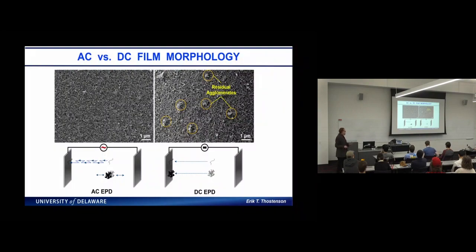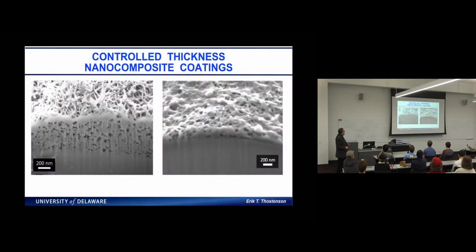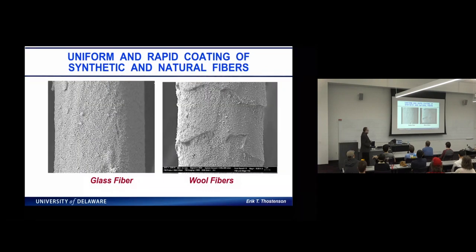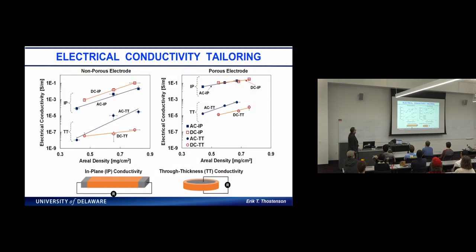And then this is just an example, as I mentioned, for the AC and DC, that for the AC, that nonlinear mobility gives us a net deposition. And we can control the thickness of that coating, and it's like this sponge-like coating. You see here it's maybe a couple hundred nanometers thick. Here, this is less than 200 nanometers. So again, it's really a fiber level coating, and we can coat not just high performance fibers, but now we can coat things like cotton or wool or polyester. And you see the wool fiber has this kind of cuticle structure, and we have this uniform coating still on that as well. And we can also have a lot of control over tailoring the electrical conductivity.